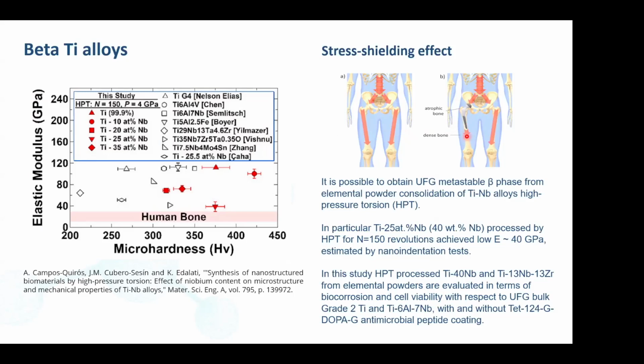modulus material like steel, cobalt, or even alpha titanium, then we will get an effect where we absorb the load only in the implant, and the surrounding bone does not get stimulated by the daily loading and unloading that we do when we move and walk. So eventually, people who are implanted with this kind of devices may get tissue necrosis around the implant, and the implant will loosen, and then this will require to be surgically removed and then reinstalled again. So if we can find materials that are lower in elasticity, more comparable to the human bone, then we can probably avoid this kind of interventions.